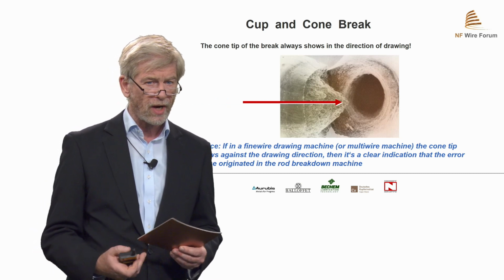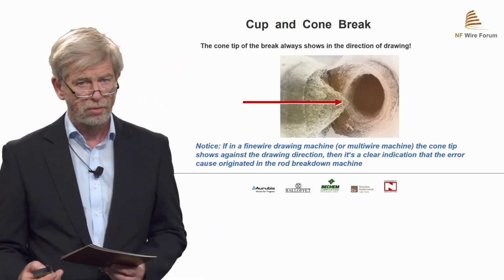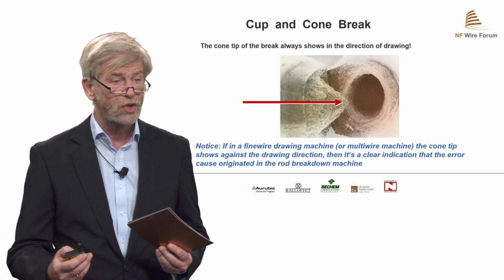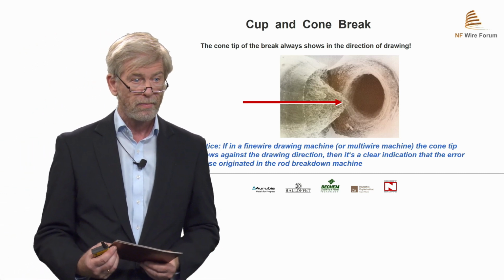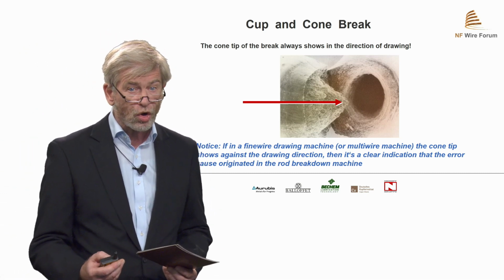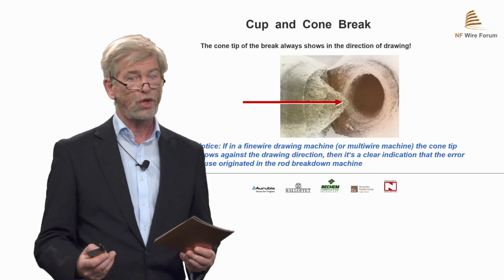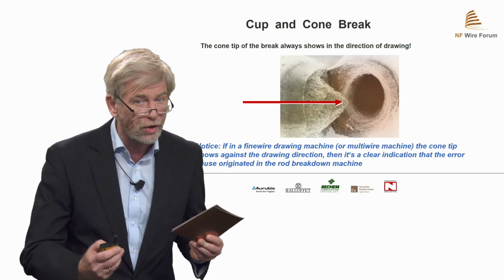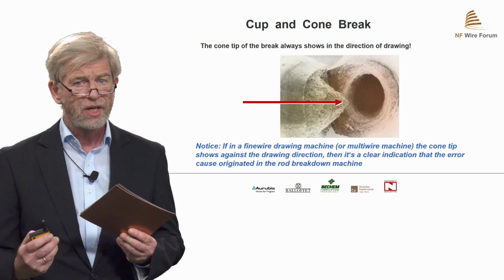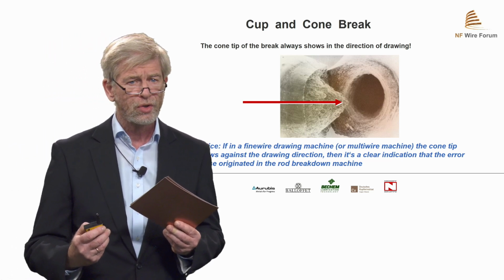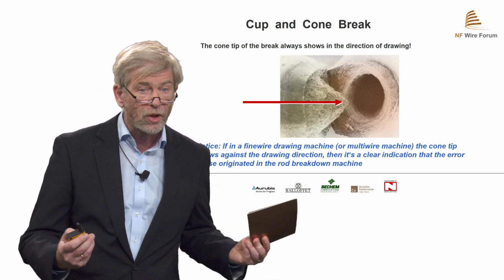So, something about the wire break. The cone tip of the break always shows in the direction of the drawing. But notice, if in a wire drawing machine or multi-wire machine, the cone tip shows against the drawing direction, then it's a clear indicator that the error cause originated in the rod breakdown machine.